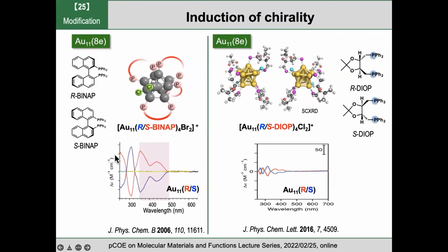And the ligand can induce chirality by using chiral ligands like BINAP or DIOP. These are bidentate chiral ligands. And by using these ligands as protecting reagents, we can induce CD activity like this. And the enhancement of CD is bigger using BINAP. So we thought that the pi electron system also contributes to the enhancement of the CD activities.